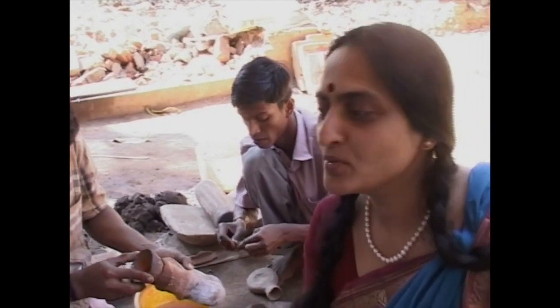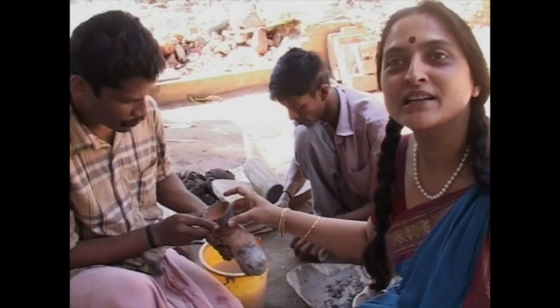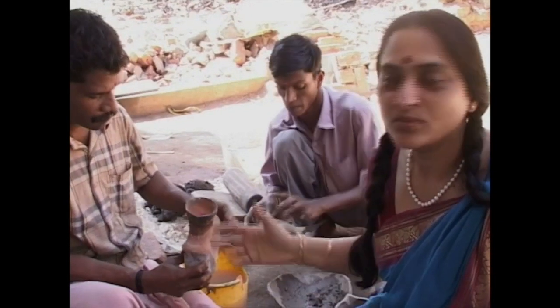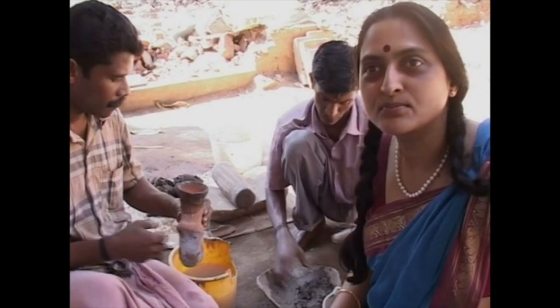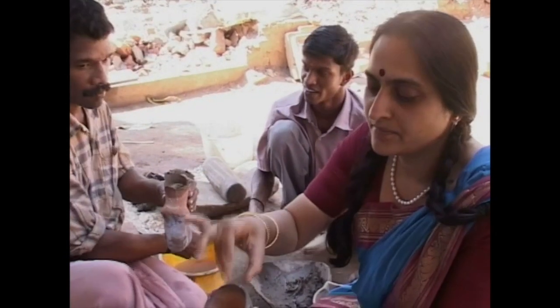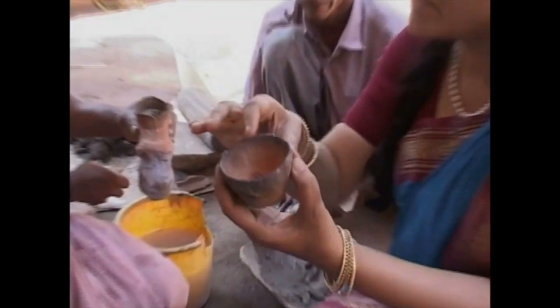I must explain this. This mold actually broke because it was heated for too long. We were waiting for Balaji to film, and so the cup of the mold was kept in the hearth for too long. What happened is it became very brittle. So that's why the temperature has to be just right. If it's too hot, then it breaks. Now he's going to repair this mold. It's almost like glass hardness, becomes very refractory. You said the temperature reaches 800, so very hard and refractory.